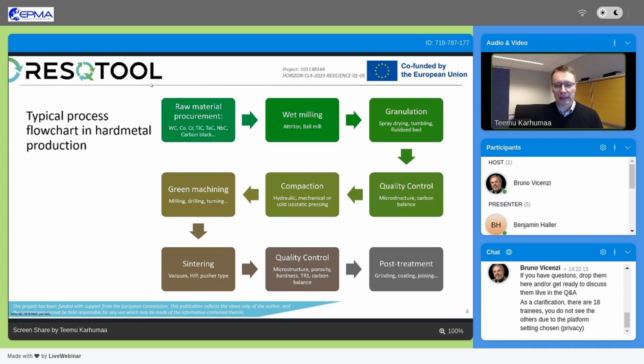The powder is compacted to give a shape and can be green machined afterwards. And the very important step for hard metal production is the sintering, as it is for any kind of powder metallurgical process, where the hard metal gets the final strength and properties. And then afterwards, there is again a quality control step to check the porosity, microstructure, carbon balance, etc. And then at the end, there might be some post-treatments like coating, grinding, joining, welding, brazing, etc.